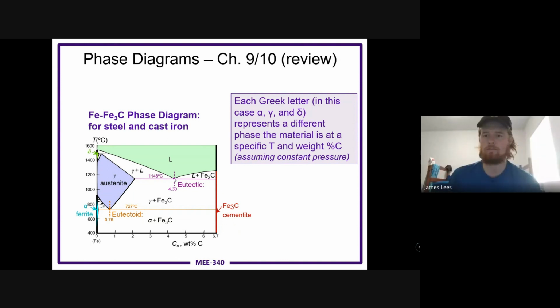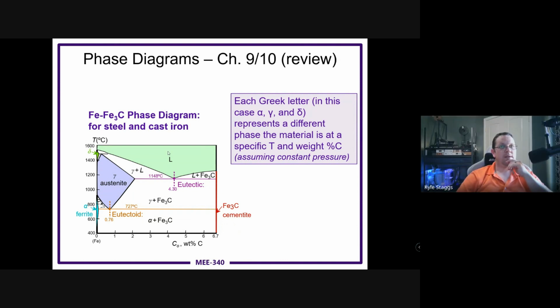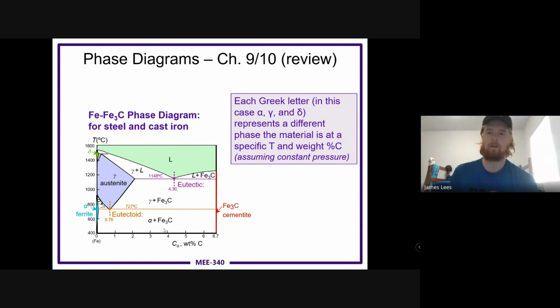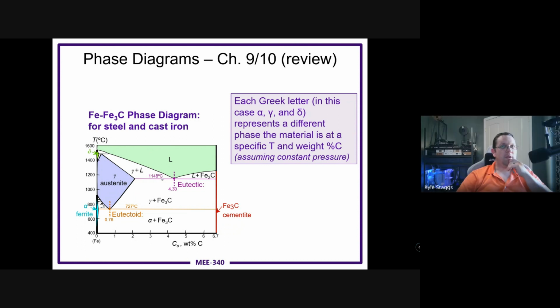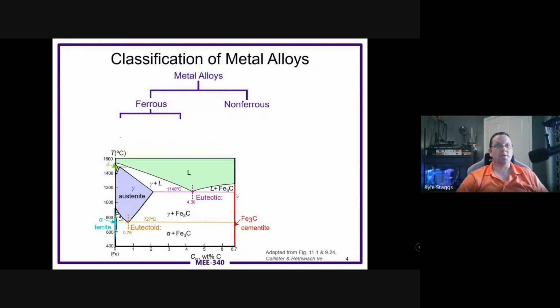Casting? Exactly, casting. So what do you guys think material-wise, what range is this? If this is like iron all the way at the left side and there's low carbon steels here and high carbon steels here, what do you guys think goes here? Medium carbon steels? You might think medium carbon steels are here, but this is actually the cast iron region. So this is irons that we cast because of their lower melting temperature. So they don't tend to have nearly the same ductility because they have way too much carbon, because we talked about some of that in the grain structure.